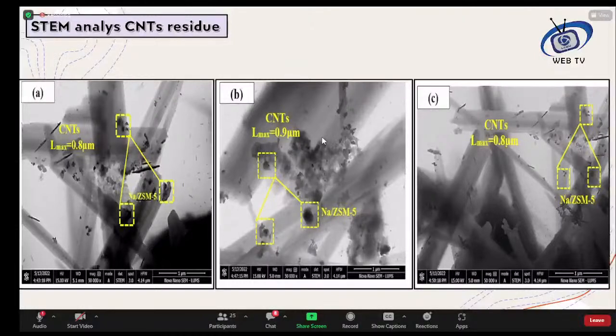And in the first case, we produced high gas and high liquid and residue. But we also see that HDPE in image A also produced amorphous products, and this is due to the high amount of the residue. It means that the reaction was not fully complete, and some residue in the form of the catalyst, amorphous carbon, or the heat susceptor was there in the structure of the carbon nanotubes.